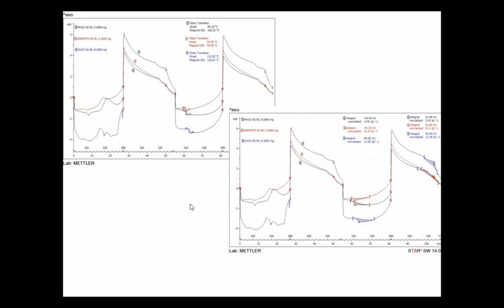After this, we tried to see their thermal stability analysis. Like I have already explained, we looked from room temperature to higher temperature. Similarly, we can go down to sub-zero temperature. We tried it up to -40 also, right? What we observed is that the 3D printed cells we prepared were able to work at very high temperature, up to 95 degrees. Otherwise, the commercial energy storage devices are not able to work at such high temperature, right? Similarly, if you see your remote batteries and cells, once you go to lower temperature, the flow of charge is not happening properly.